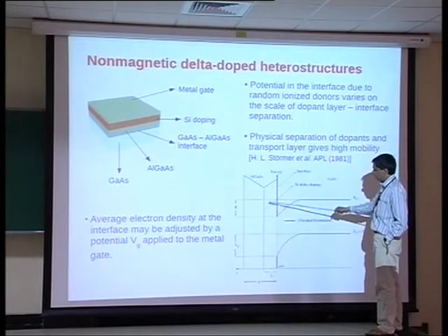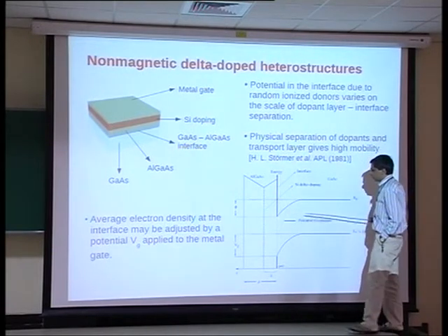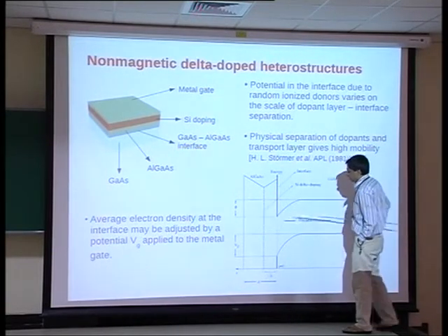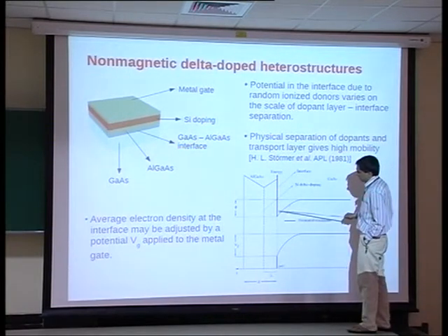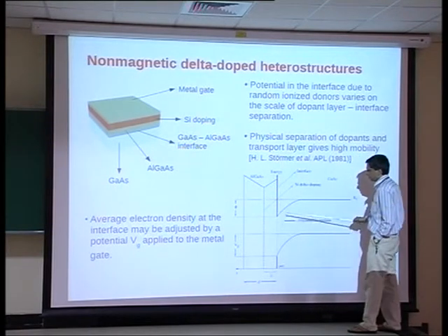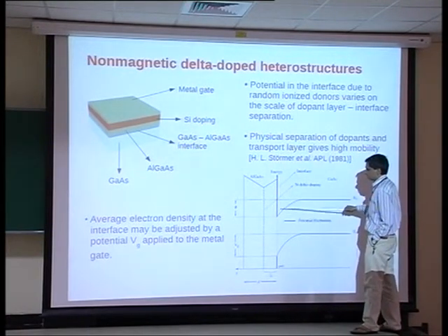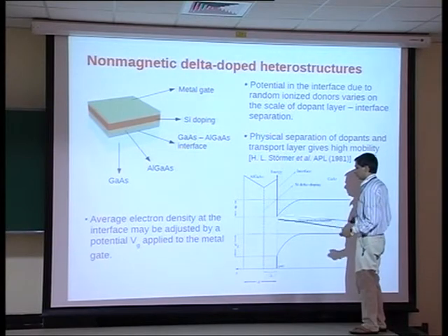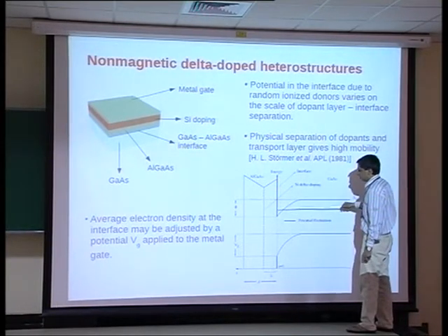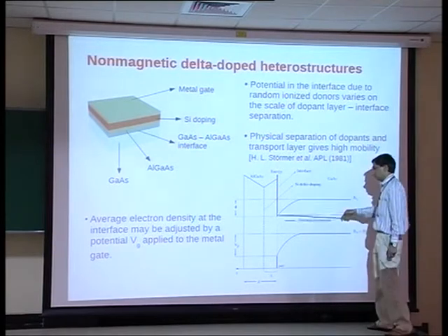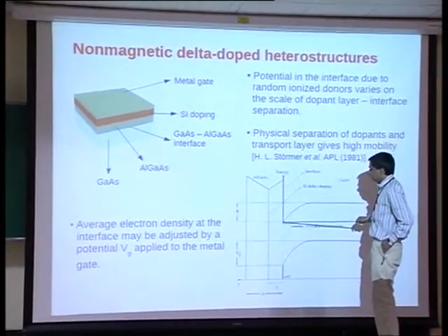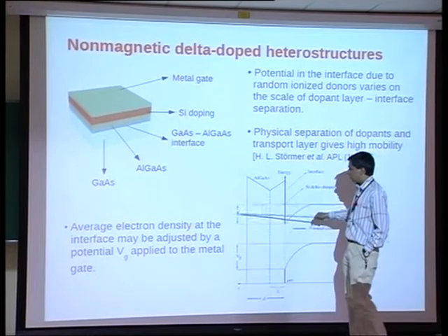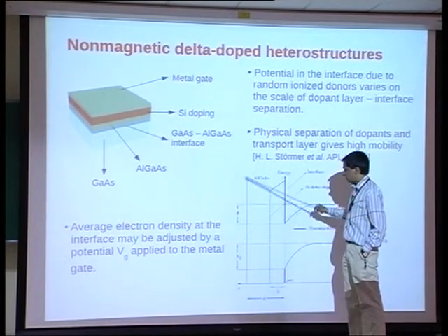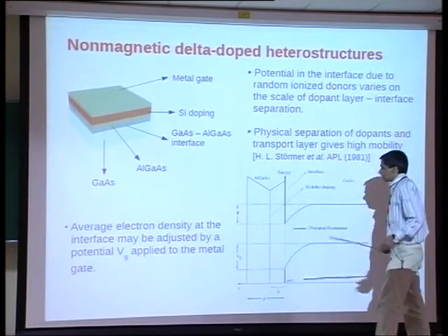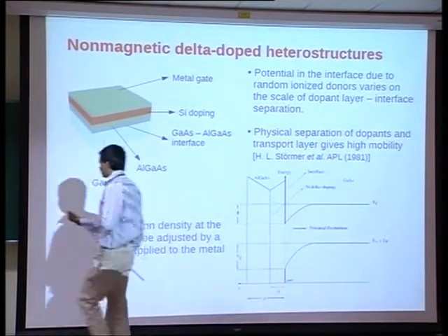It shows a dip here because you have to keep the chemical potential equal across the two materials, and whenever the bottom of the conduction band dips below the Fermi energy, you acquire electrons here, and that's the source of your two-dimensional electrons, because they are confined in this direction, but they can freely move in the direction perpendicular. And you can move the bottom of the conduction band through a gate potential applied here. So this gives us great control over the electron density.